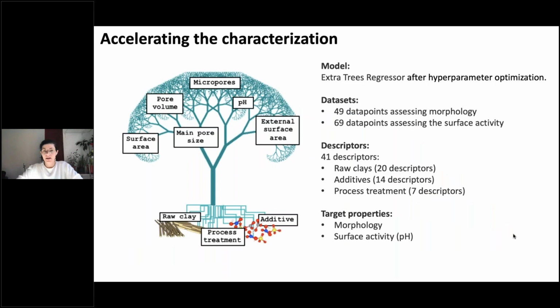In particular, 6 independent models were built and used for predicting the surface area, pore volume, main pore size, micropore content, and external surface area as morphological targets, and the surface activity in terms of pH, as shown on the leaves of the tree. We fed our tree-based machine learning models, that is the body of the tree, with some information we collected about the raw clay, process treatment, and additives depicted at the roots of the trees. The machine learning model that we implemented is an extra tree regressor after hyperparameter optimization.